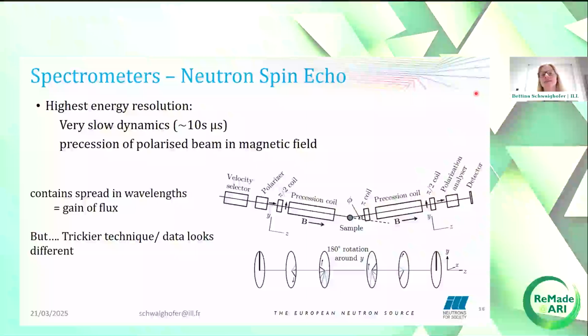However, there is a third technique, neutron spin echo spectroscopy, which allows us to reach an even higher energy resolution without losing the neutron flux completely. It gives access to very slow dynamics in the tens of microseconds, and it uses the spin of the neutron. Here is a schematic diagram of how a spin echo spectrometer is laid out. The velocity selector selects a range of wavelengths with 10% monochromaticity. So it's much less monochromatized than for the previous instruments I discussed.